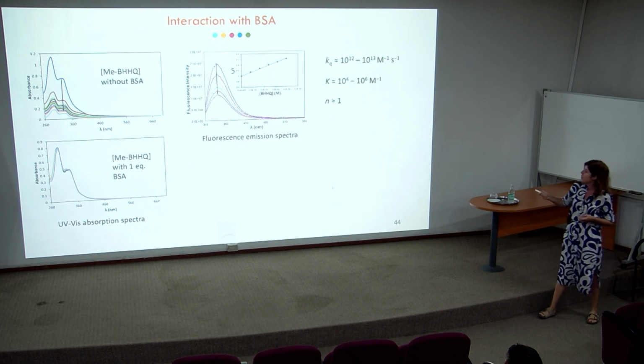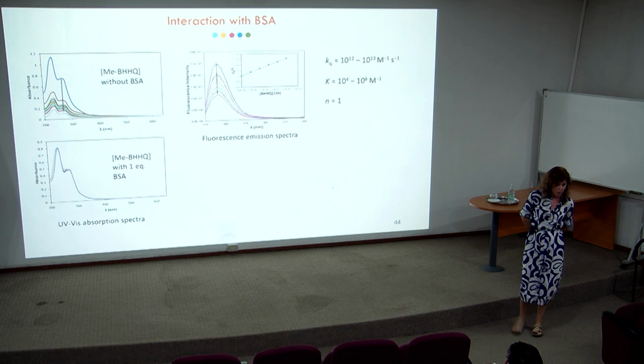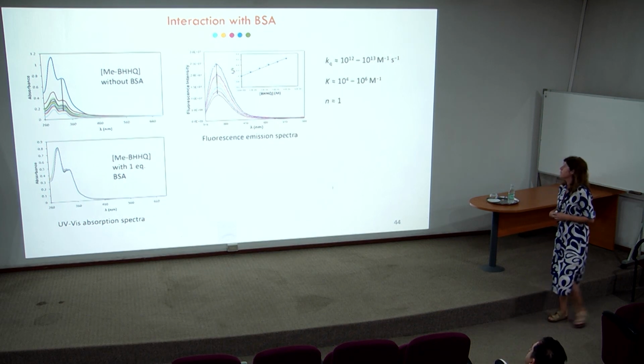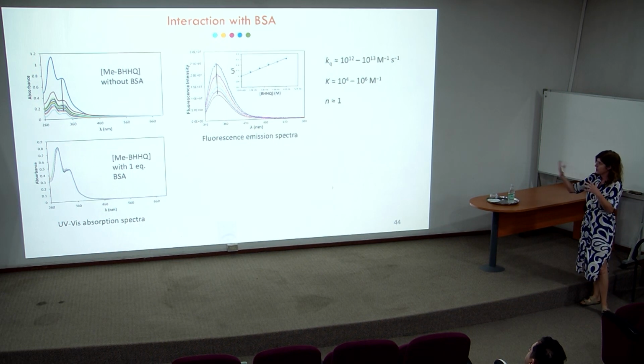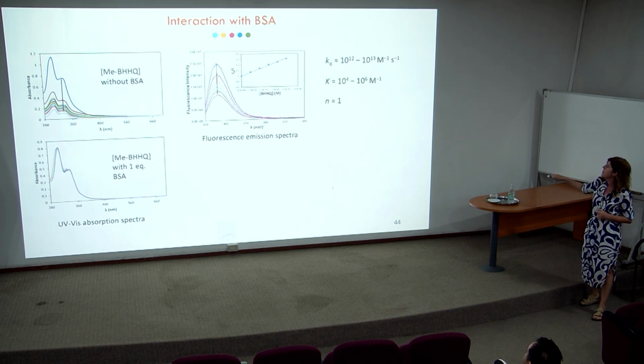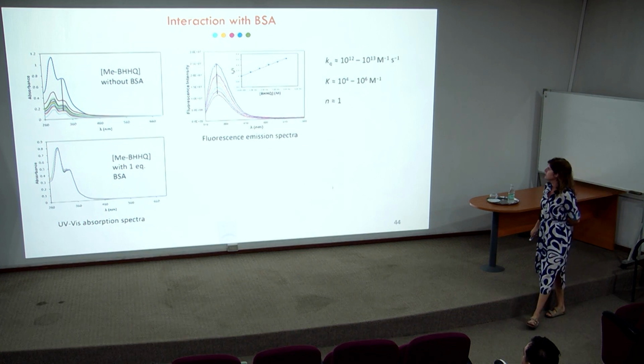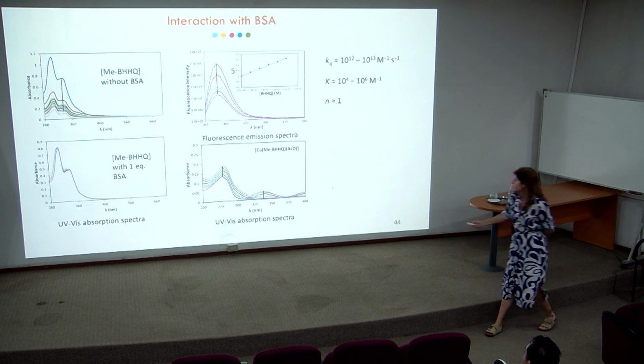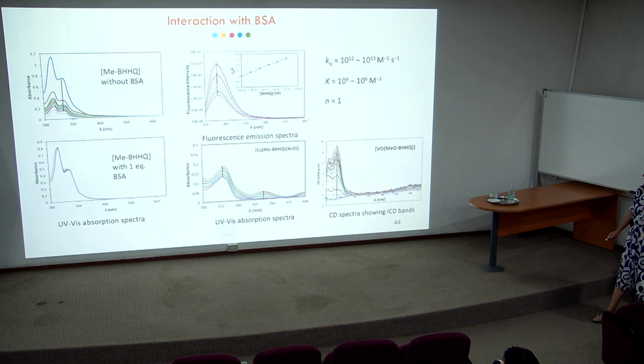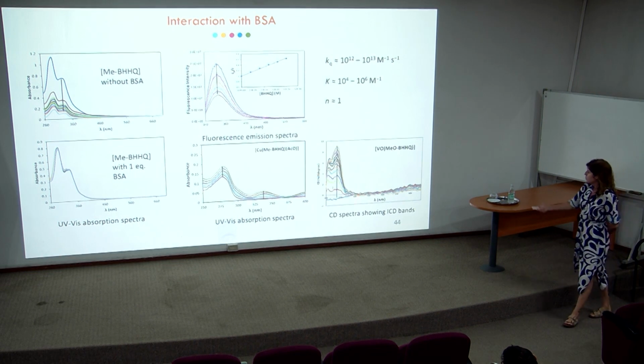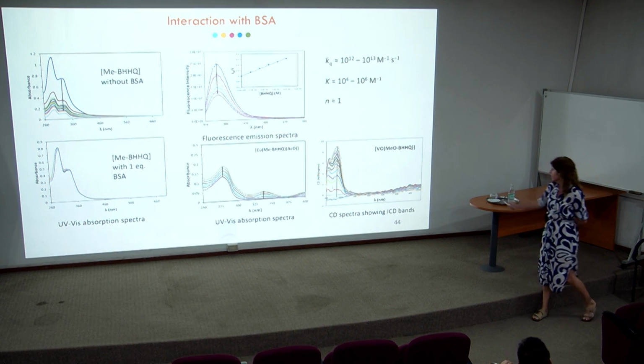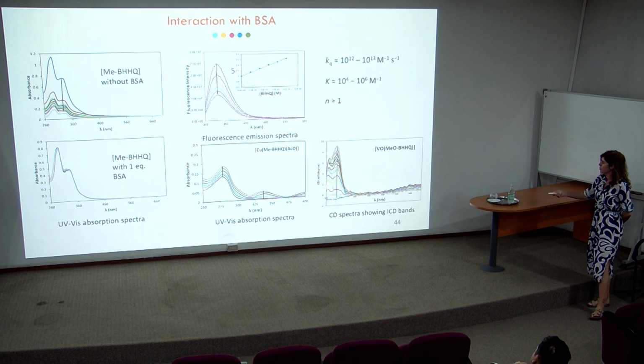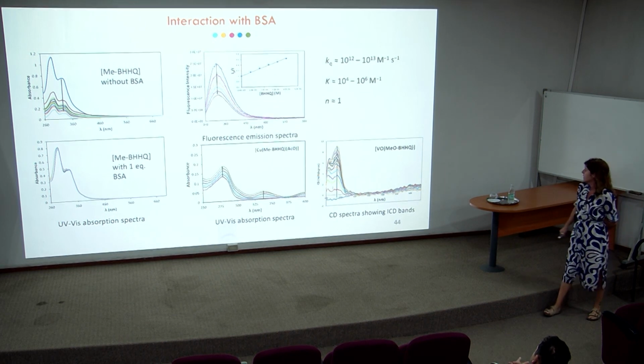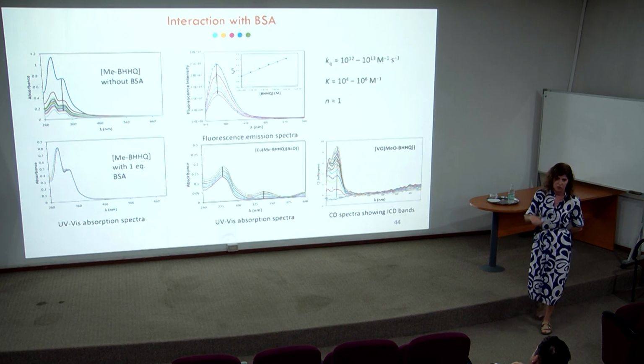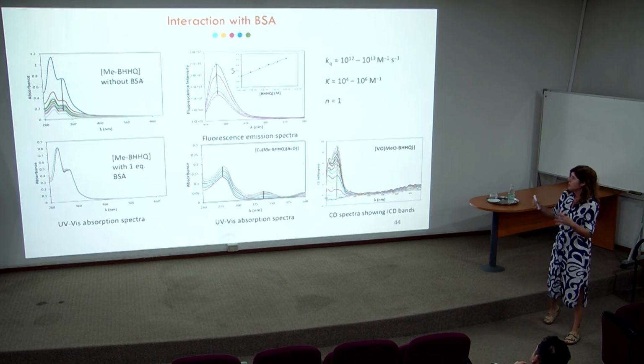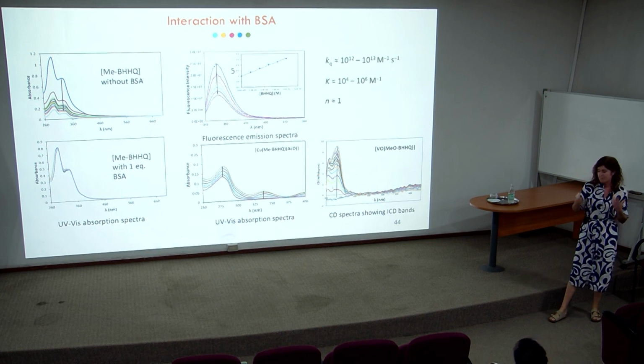We used also fluorescence emission spectra, in which we titrated the complexes or BSA with increasing amounts of the complexes to determine binding constants. We also used UV visible absorption spectra and CD. You can see here the interaction of the vanadium complex with albumin and the development of a new induction band where the complexes have charge transfer bands. So all these compounds can be transported in blood in the serum by albumin.